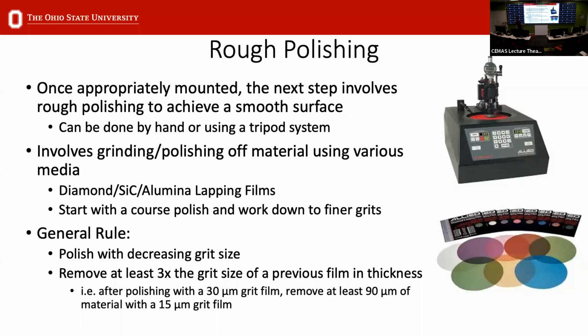There are these polishing films that have different materials that are used to remove material. You can use something like diamond, silicon carbide, or alumina. The choice just depends on your sample itself. If you have a very hard material, you definitely want to use diamond, but those are more expensive than the alumina lapping films. With this, you want to do a coarse polish at a higher grit film, and then work your way down to a finer grit film to progressively remove the damage from the previous grit.